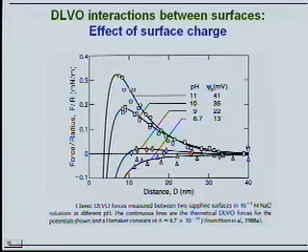So you can see that what people have done here is they have changed the pH, and they have measured the force versus distance curves. At large pH, you have large charge, and the surfaces repel each other strongly. Smaller pH, smaller charge, smaller repulsion. Even smaller pH, even smaller repulsion. And then I told you that at about 25 millivolts or so, the electrostatic repulsion really becomes pathetic. And you can actually see this here. At 20 millivolts, the energetic barrier really doesn't look much like a barrier already.